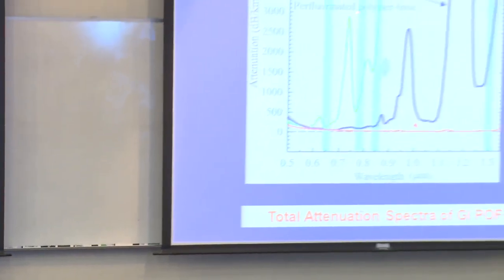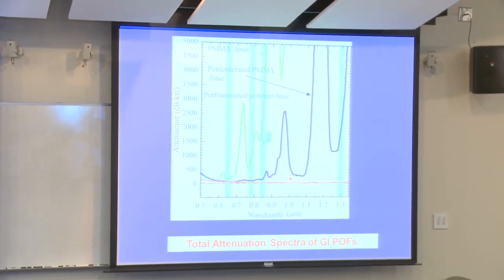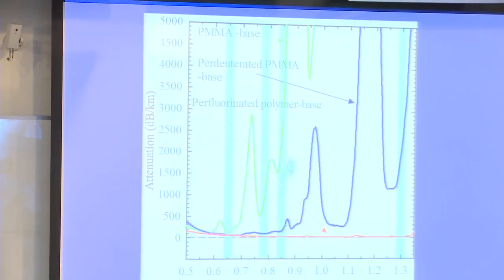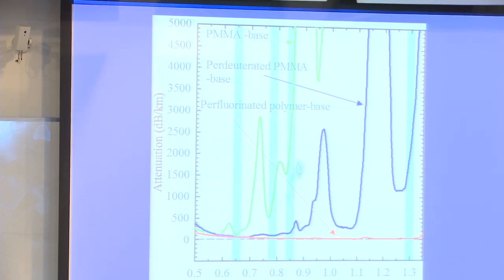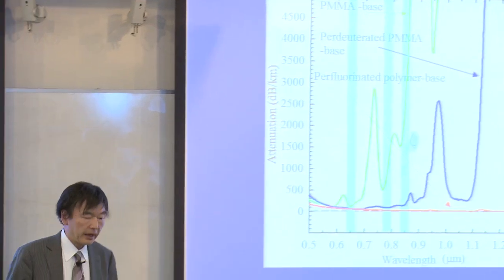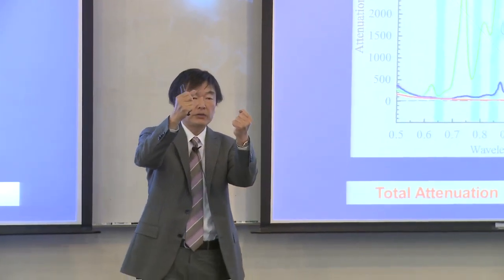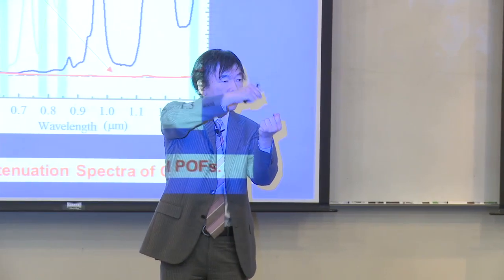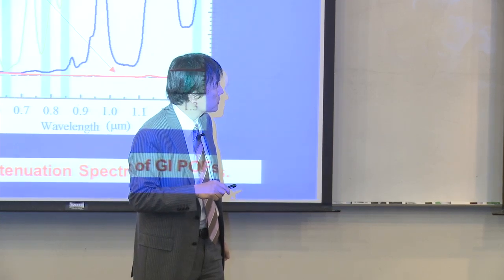Anyway, the material I use is the perfluorinated polymer. In the case of the PMMA, that is the green curve here, you suppose the PMMA is a transparent material in the visible region. That's true, but not in the infrared region, because PMMA has hydrogen. There's a carbon-hydrogen bonding. Hydrogen is the lightest atom, so the frequency of the stretching vibration is very fast. So the fundamental vibration occurs at 3.4 micron. And this peak corresponds to the overtone of carbon-hydrogen stretching vibration, the fourth, the fifth, and the sixth.